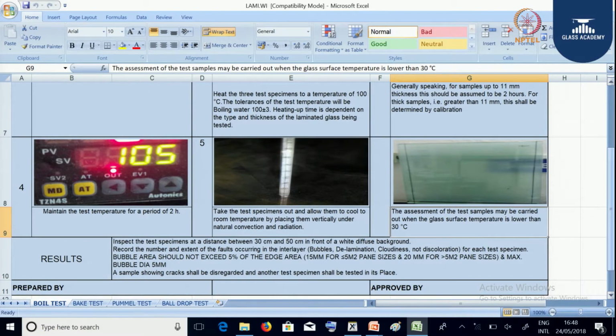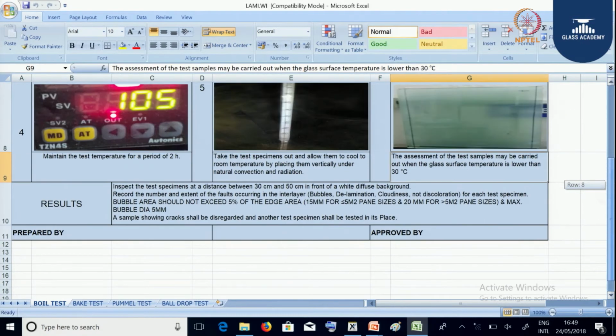Once the 2 hours is completed at 100 degrees centigrade, we will be removing the glass from the boil test chamber, and with a background we will inspect the glass for bubbles, haziness, and discoloration. The result is, inspect the test specimen at a distance between 30 centimeters and 50 centimeters in front of a white diffused background. Record the number and extent of faults occurring in the interlayer in the form of bubbles, delamination, cloudiness, discoloration.